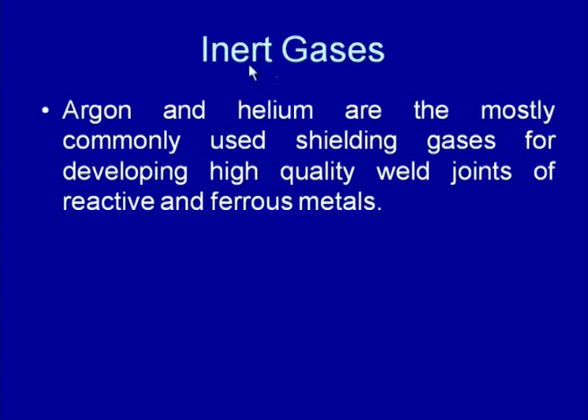So use of the CO2 under the high temperature conditions generates gases like CO and O2, which in turn adversely affect the quality and the soundness of the weld joint. If we see the inert gases, then among the inert gases, argon and helium are the most commonly used shielding gases for developing high quality weld joints of the reactive metals and the ferrous metals.